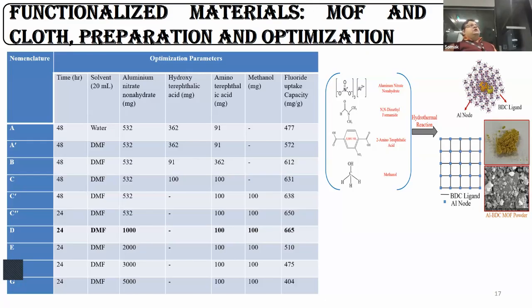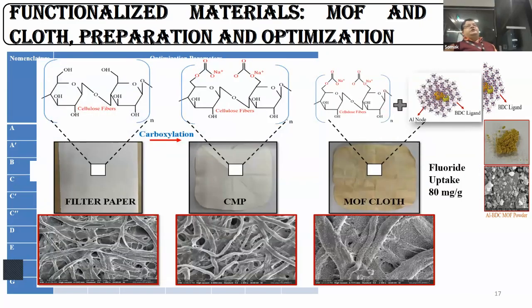In comparison to some of the MOF-based solvents. But however, the yield of the MOF is very low, and people are finding means to increase its yield. So instead of finding so much of a detailed network, we try to take the shortest route. With the help of this shortest route, we synthesize this MOF and utilize it to immobilize on a surface, and that surface was a filter paper.